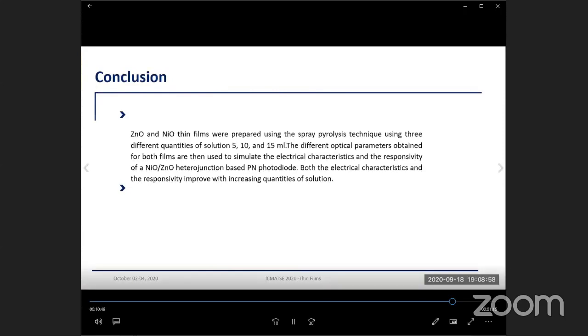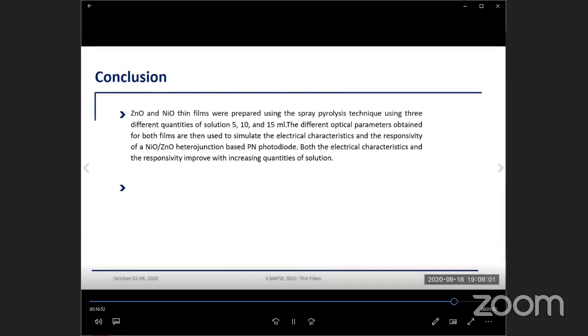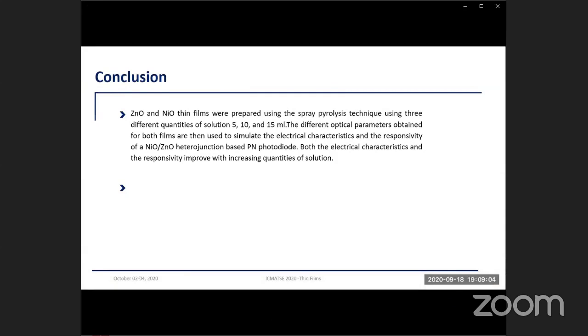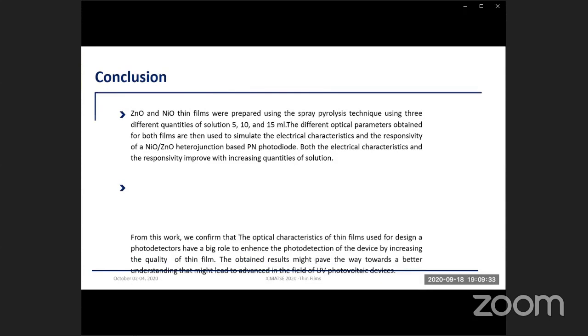Finally, the conclusion. Zinc oxide and nickel oxide thin films were prepared using the spray pyrolysis technique using 3 different quantities of solution, 5, 10, and 15 milliliter. The different optical parameters obtained for both films are then used to simulate the electrical characteristics and responsivity of a nickel oxide zinc oxide heterojunction-based PN photodiode. Both the electrical characteristics and the responsivity improve with increasing quantities of solution.